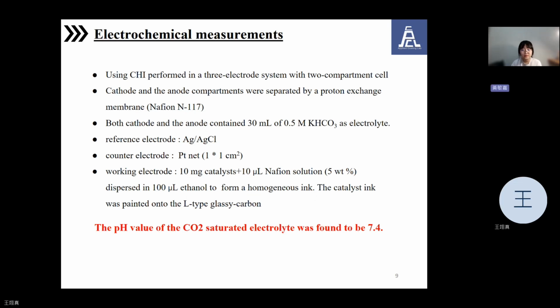For the electrochemical measurement, it's using the CHI performed in a 3-electrode system with a 2-compartment cell. The cathode and the anode compartments were separated by a proton exchange membrane, the Nafion N117. It used potassium bicarbonate as the electrolyte, Ag/AgCl as the reference electrode, and Pt net as the counter electrode. And we drop the ink, mixed from the catalyst and Nafion, on the working electrode.